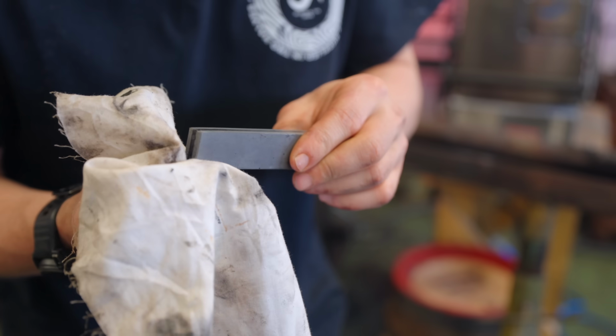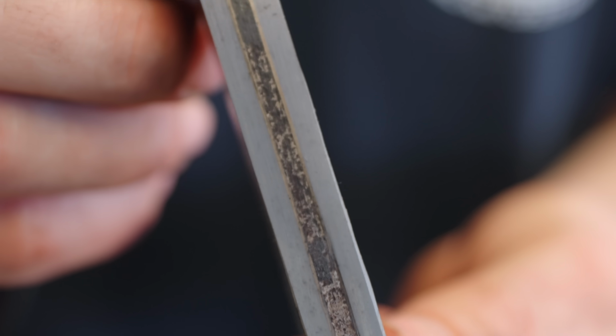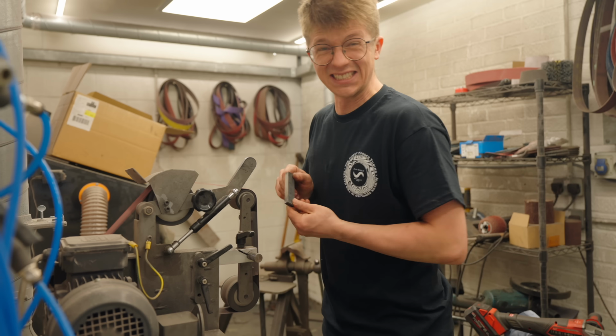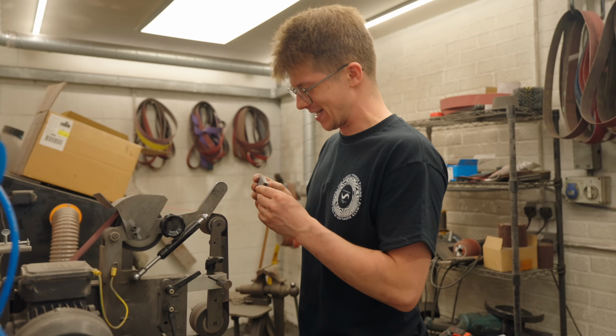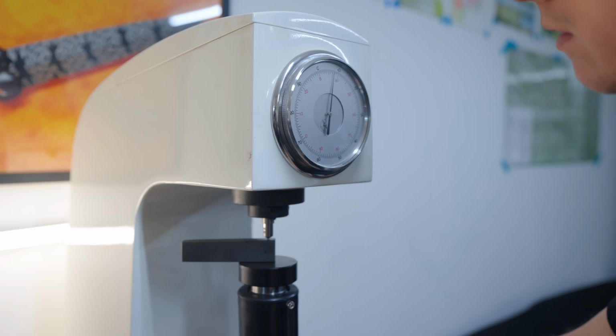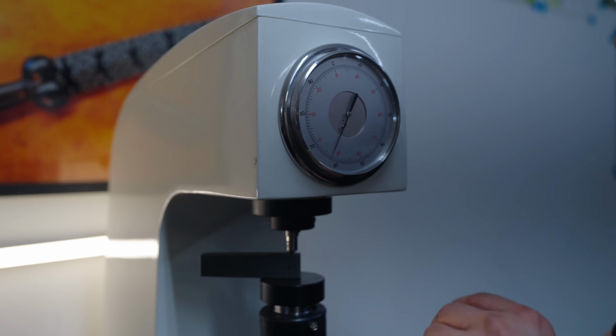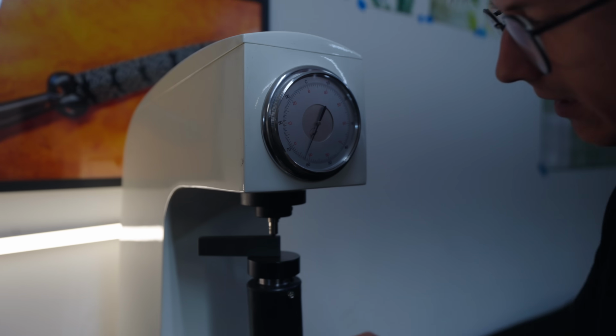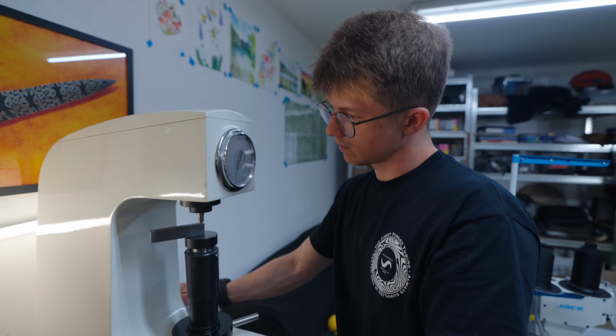This is our quenched sample. It appears to still be in one piece. Can't see any cracks yet. Definitely hard, because it does not grind very easily. It looks good. Ooh! 62 Rockwell. 65. 63. Very adequate hardness there after the quench.